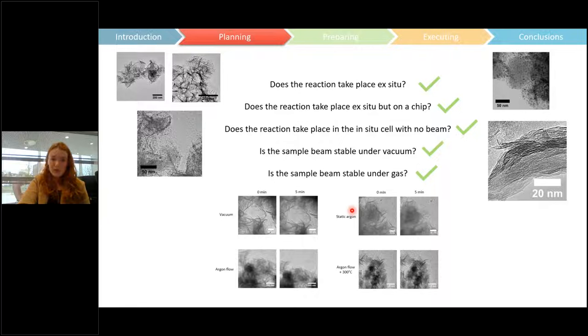Then, as we saw before, I performed those experiments where I varied the gas and the temperature to see whether it was stable under argon, to see whether it's stable under hydrogen. I ran a bunch of experiments to see if my sample survived with beam and gas, and this is really, really important. Thankfully, there was hardly any influence of the beam and the gas, but it can really be a make-or-break experiment, and it's really disappointing when it goes the wrong way. Don't get me wrong, in a lot of my experiments I have seen it go the opposite way, and it's a bit of a killer, really.